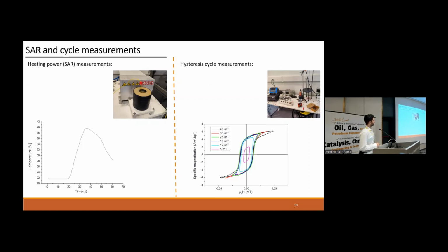And also, we did some hysteresis cycle measurements. In this case, we would apply the magnetic field onto our sample, and we would measure the magnetic response of the sample, as we can see here. So we have the system magnetization as a function of the applied field. And so we're going to have these cycles. And the heat that's being generated with this mechanism, the hysteresis cycle mechanism, can be calculated from the surface area of each cycle. So the bigger the cycle's surface area is, the more heat is being generated.